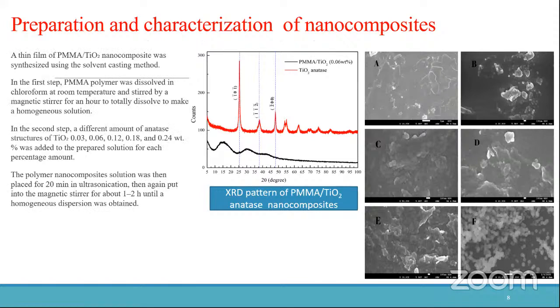So the thin film was prepared using the solvent casting method. The powder was dissolved in chloroform at room temperature, stirred by a magnetic stirrer for 1 hour to make a homogeneous solution. Then different concentrations of titanium dioxide nanoparticles were added to make different samples. The polymer composite solution was then placed for 20 minutes in the ultrasonication, then again put into the magnetic stirrer for 1 to 2 hours until the homogeneous dispersion was obtained. The resulting solutions were then poured into separate Petri dishes and left to dry for 2 days.